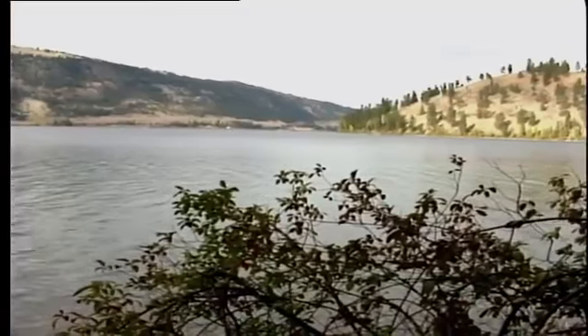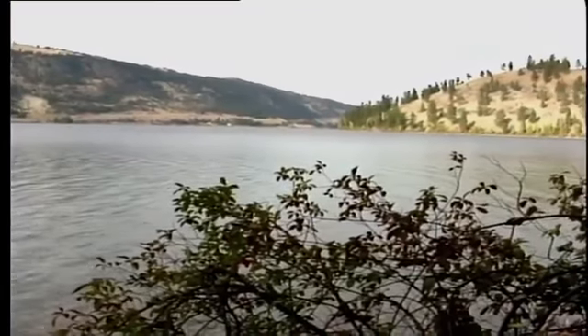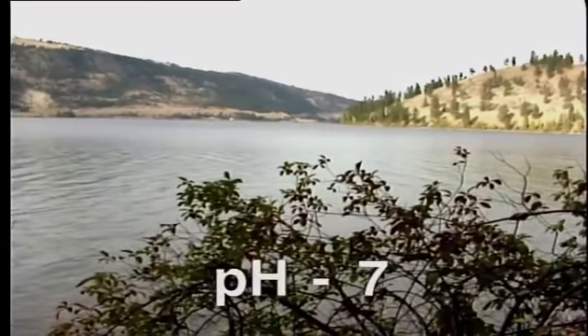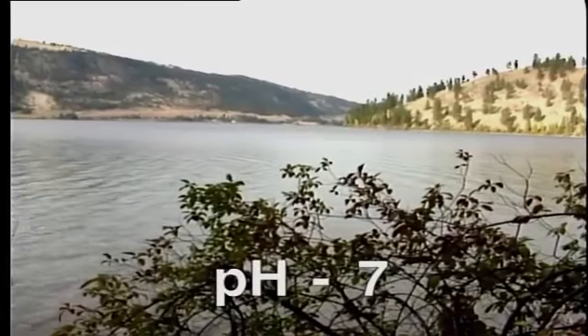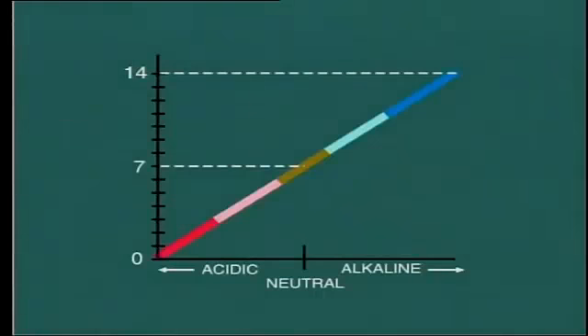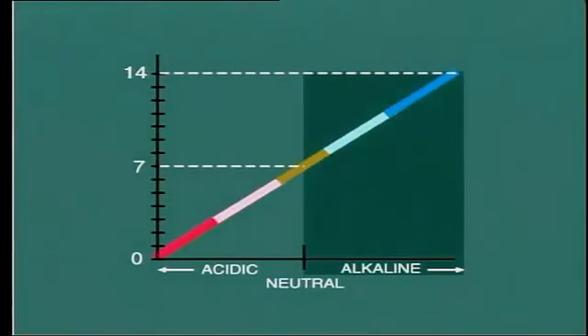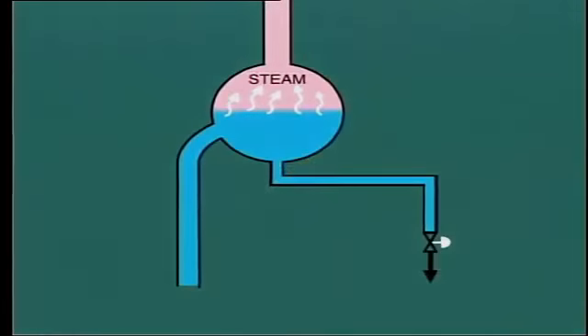Most natural waters in fresh lakes and rivers usually have a pH value close to 7, unless, of course, pollution is present. So if we are to prevent acidic corrosion inside our boiler, it is obvious that the pH value of the boiler water must be maintained above 7. Actually, to be on the safe side, and to allow for the fact that there are probably variations within the mass of water, the normal established limits for boiler water pH are within the range 8.5 to 10.5.